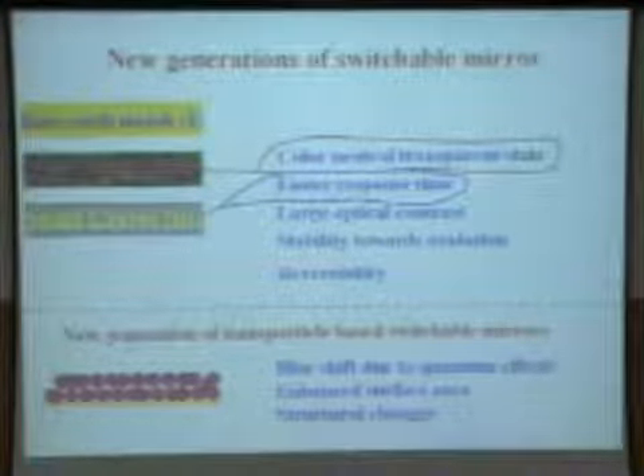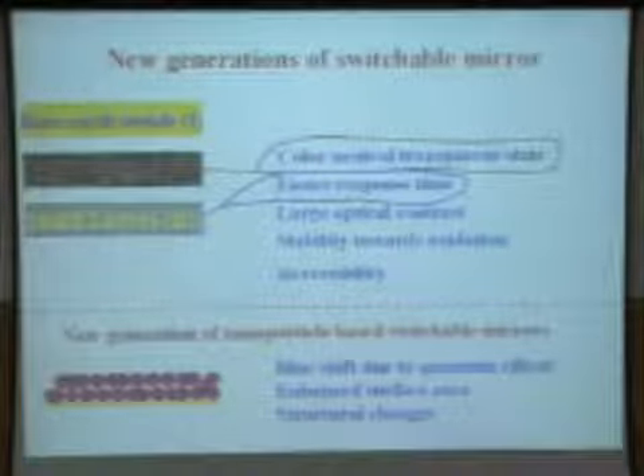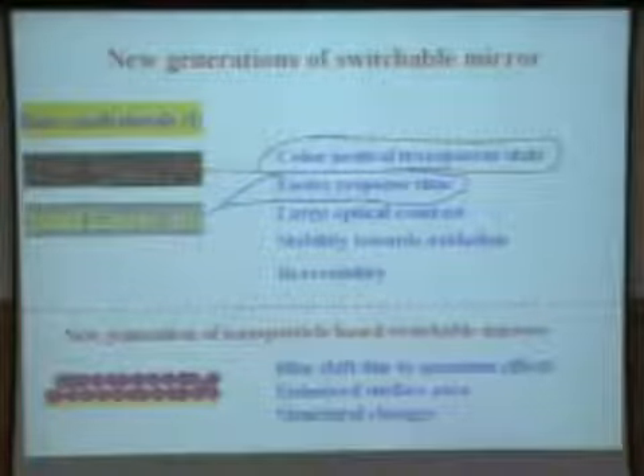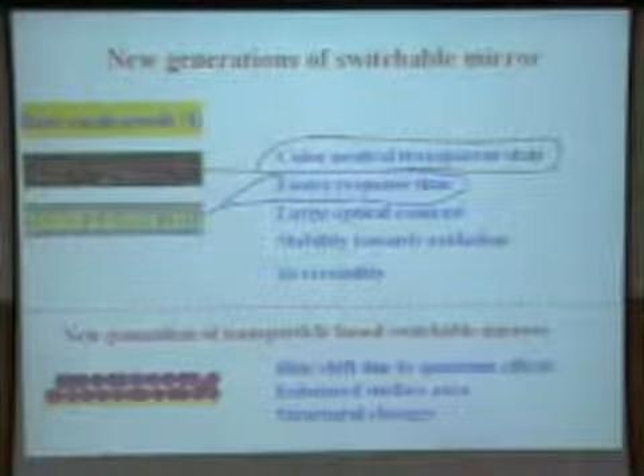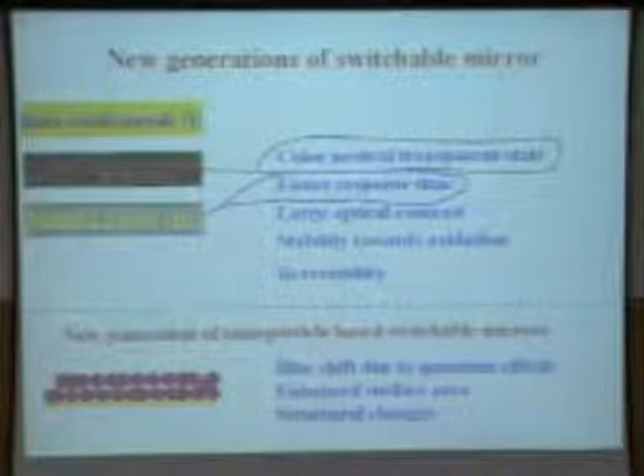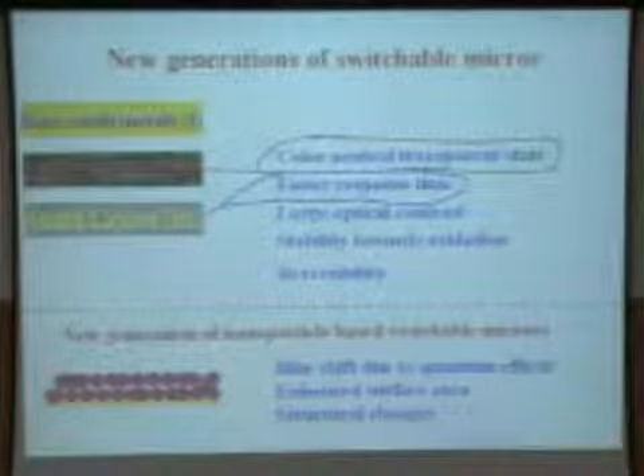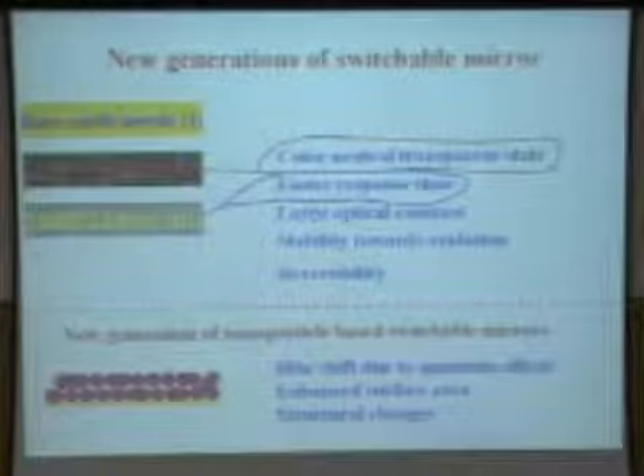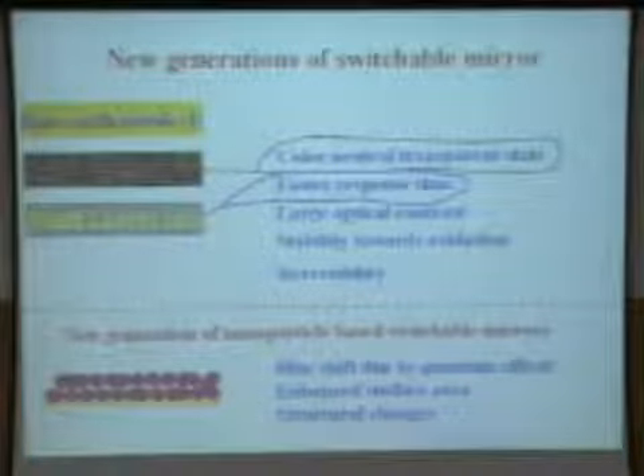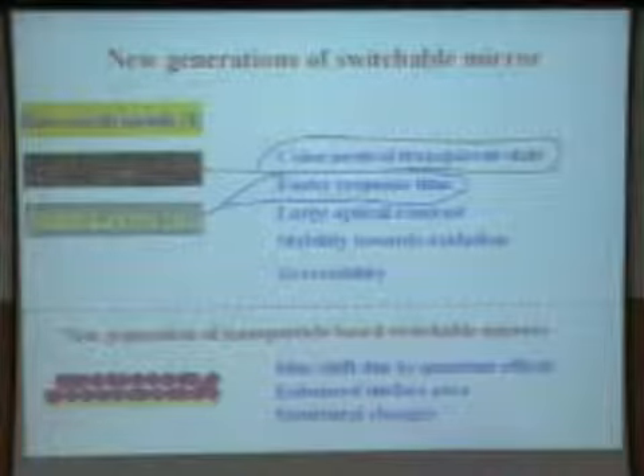The only thing we were not sure about was that many times in solid state materials, when you go to smaller dimensions, there is a modification in the crystal structure, called size-induced structural transformation. For different reasons, the crystal structure of the material in bulk form and in nanoparticle form can change. What will be the effect of that change in crystal structure due to size on its interaction with hydrogen? We were not very clear. But the first two effects, we were very sure, would result in improvement in all the switchable mirror properties. I'm very happy to tell you that we were in fact the first group to use nanoparticles of rare earth materials for this particular application.